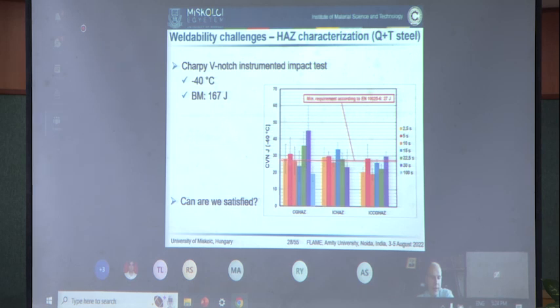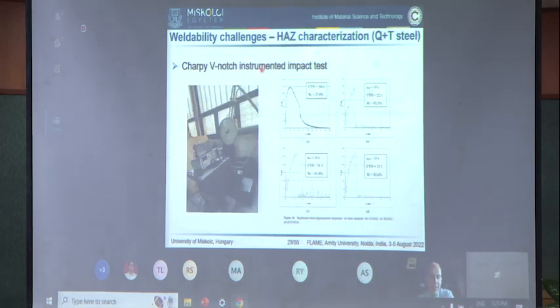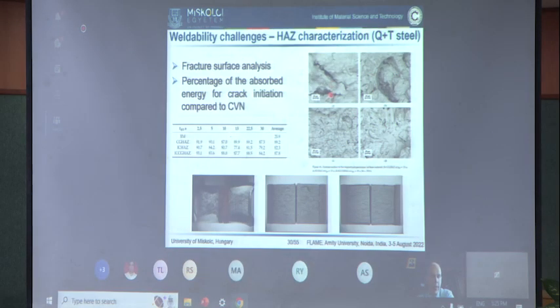Although the requirement is often fulfilled and we are above the requirement of 27 joule, we can see during instrumented Charpy V-notch testing that the heat-affected zone generally behaves fully brittle. There is no stable crack propagation in the measured force-displacement diagrams compared to the base material, where you can clearly identify stable crack propagation in the graphs, and generally only a little unstable crack propagation is observed. But in the heat-affected zone, the coarse grain and intercritical heat-affected zones always behave very brittle, as you can also see in the fracture surface of the Charpy specimens. There is no real plastic deformation, so it's a very brittle cleavage-like fracture.